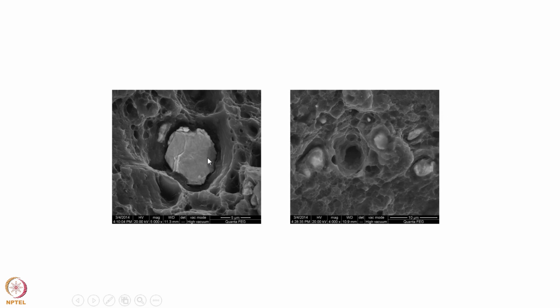So this is indicating a ductile kind of failure where the interface bonding was good and the void nucleation mode was particle cracking, okay? But here you can see a void over here which is corresponding to the size of a particle, okay? So this tells you that there was a particle sitting over here which has actually pulled out, right? And that also indicates towards the fact that the interface is weak over here. The interface bonding is not strong, and that is why when the composite was loaded, this particle is pulled out, right? So here the void nucleation mode is the second mode that we talked about, that is through particle pull out, and this happens when the interface bonding is not that strong.